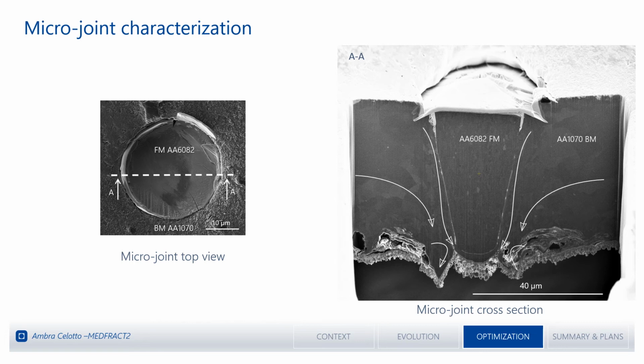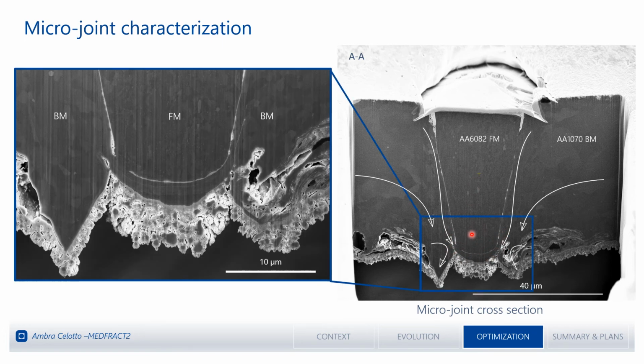So by considering that the filler metal is way stronger than the base metal, which is a pure aluminium alloy, the filler metal tip, while it was advancing, was also smearing some material pieces from the walls of the hole and dragging them down towards the bottom and starting to build up material in front of the filler metal tip while it was advancing. So this is why this joint actually has a bottom that was not designed, but this is actually a sign of really, really heavy deformation between the two components. And also, as marked here with the arrow, the original corners of the holes were opened up towards the external side.